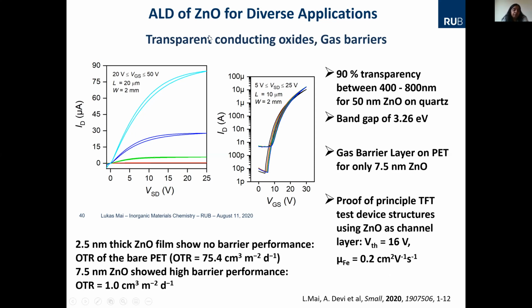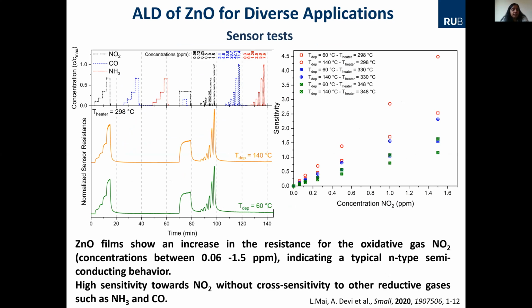So this material, as in the case of aluminum oxide, has several functionalities as gas barriers, as transparent conducting oxides, and also from the UV, we see that they are highly transparent. So the final application was, okay, sensing, because that was one of the main project goals. And we found that this particular material system that we grew at different temperatures shows some sensing activities for different gases. And particularly for NO2, we found that they have higher sensitivity.